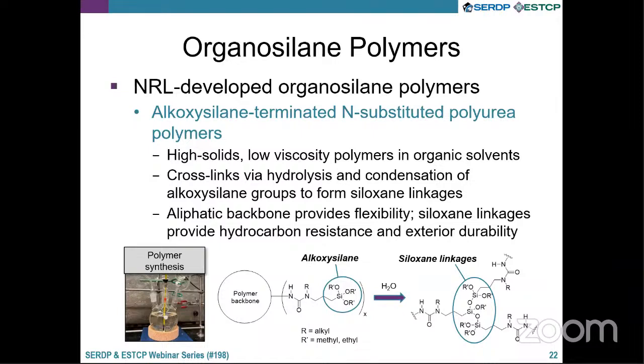These polymers can be synthesized as high solids in organic solvents while still retaining low viscosity. The mechanism of cure is that these alkoxysilane groups, which I have circled here, react with atmospheric moisture. They hydrolyze to form silanol linkages, and then adjacent polymers cross-link with these linkages to form this rigid siloxane backbone, as shown after the reaction arrow.